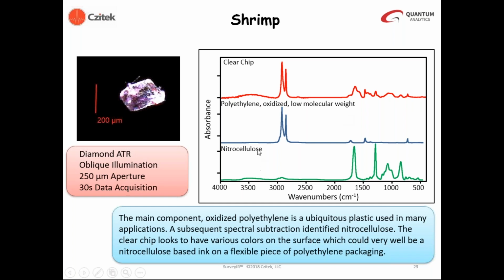The polyethylene material is shown in the middle spectrum. We were also able to identify a secondary component, nitrocellulose, and there's a third component that is present that we were not able to identify in this case. So the samples can be more than one material, and although we could only identify two components, we could see that at least three components were present in this one small 200 micrometer particle.